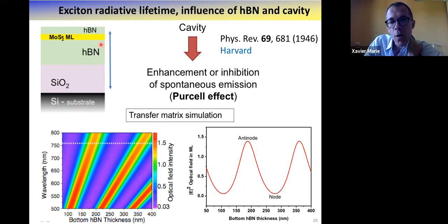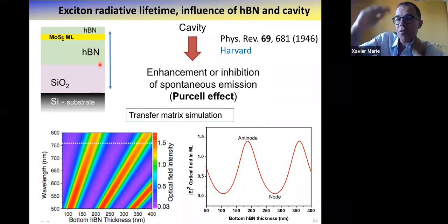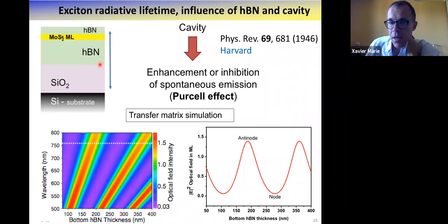And this is what we will change in our structure: the bottom hBN thickness. We measure by AFM the thickness before we fabricate the van der Waals heterostructure. So you see, for the emission wavelengths of the monolayer, which is more or less here, with this thickness of hBN, about 180 nm typically, you will be at the antinode of the optical field intensity, whereas for 250 nanometers, you will be at the node.